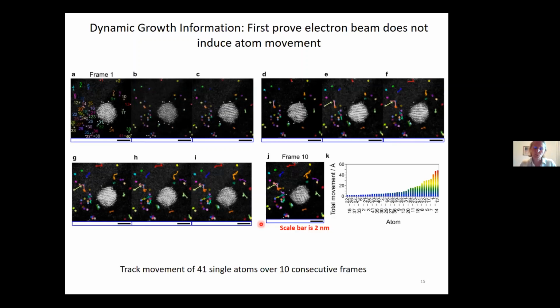And for these experiments, what you do is you image once, then you go and do your second deposition, then you go and image twice. So you only do one scan and you use the same imaging conditions. Here we have a nanoparticle and 41 atoms, and we imaged that same area 10 times. So this is effectively like capturing 10 frames of a movie, and we were looking to see what's moving around due to the electron beam. We're not doing any electrochemistry. This is just looking at electron beam induced movement.